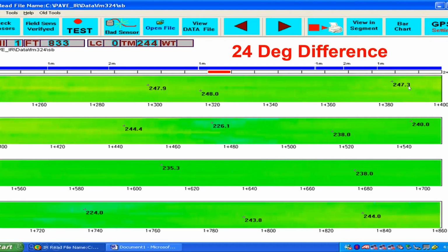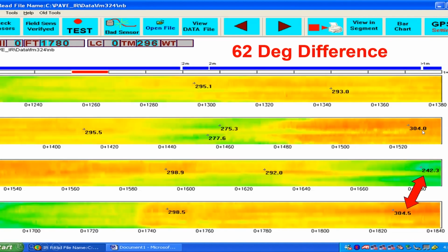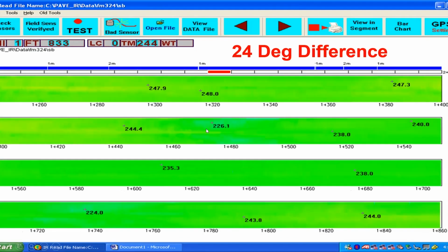Whereas with warm mix, because of the thermodynamics of the material and the fact that the cooler it is, the less rapidly it continues to cool, then we have a much lower delta between the beginning of the load and the end of the load. And there's a definite advantage to that. So typically you can see load segregation, thermal segregation, meaning this part of the pavement wears out at a different rate than this part of the pavement, and that's decreased.